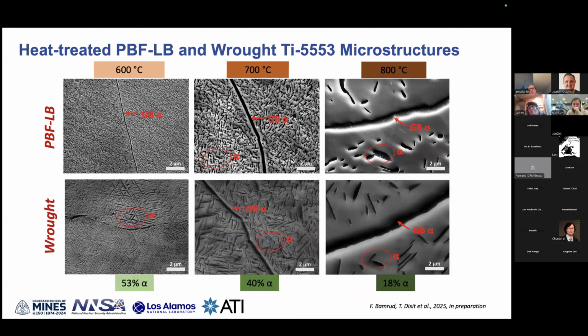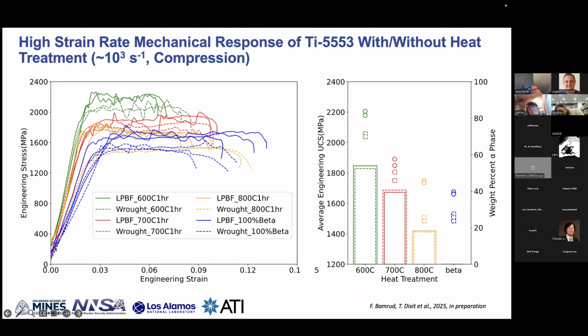More recently, we've done some work on the alloy Ti-5553. In this case, we heat treated the microstructures to have different extents of alpha phase. Here we're comparing powder bed fusion, laser beam, to wrought. And in this case, we're more interested in the dynamic material properties that we get out the other end with and without heat treatment.